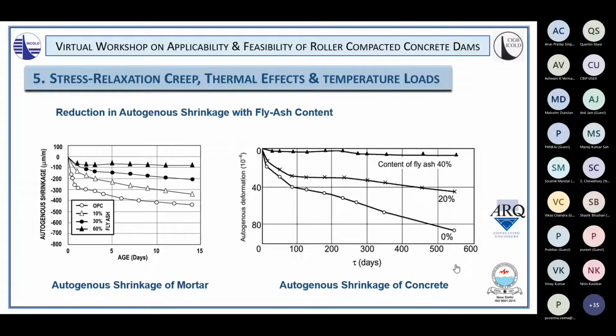So on the left hand side we see just mortar, and we see a situation with an OPC, which is the bottom line, where at 14 days you might get an autogenous shrinkage of mortar of the order of 410, 420 microstrain. When we effectively dilute that with 60% fly ash, that same situation, autogenous shrinkage in the mortar at 14 days reduces to something like 90, 95 microstrain.